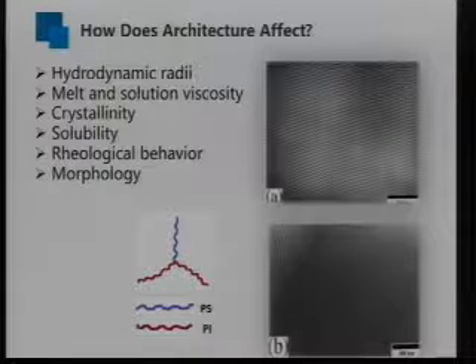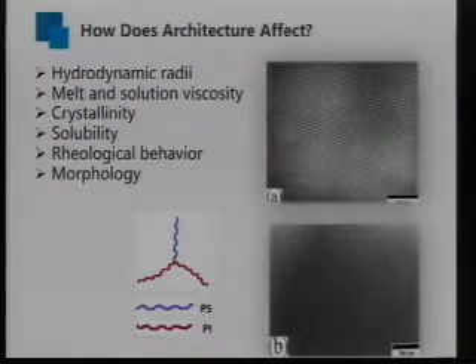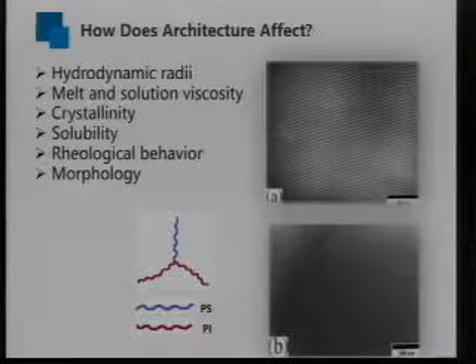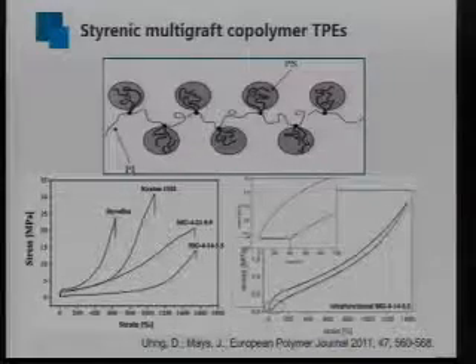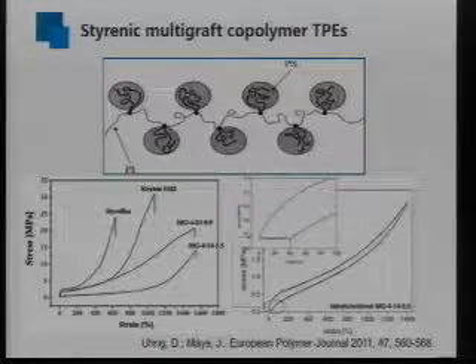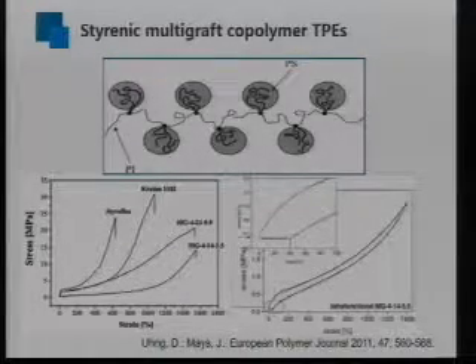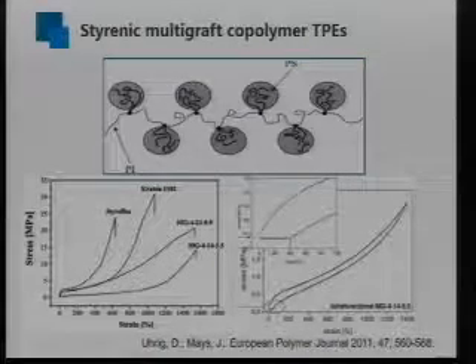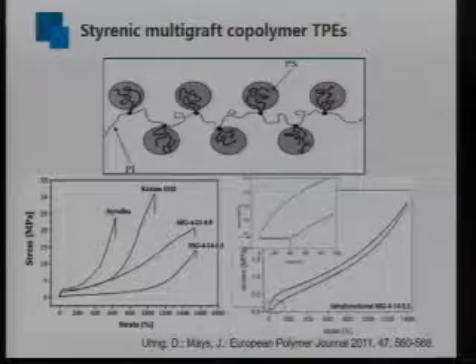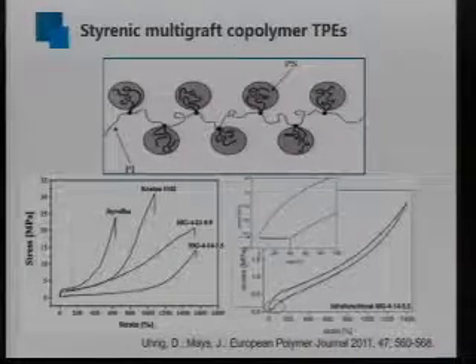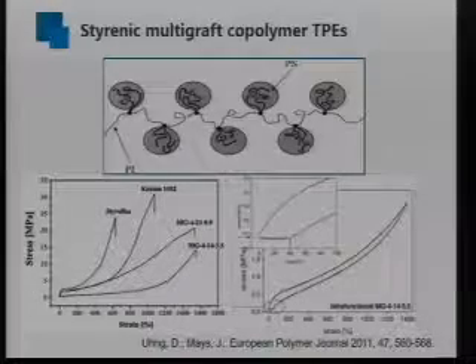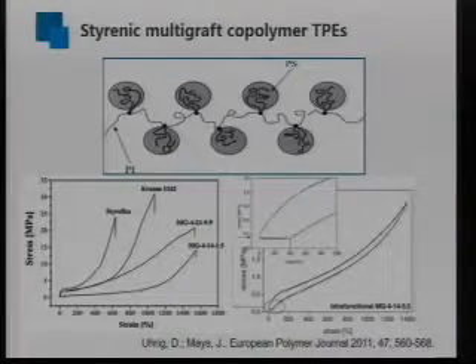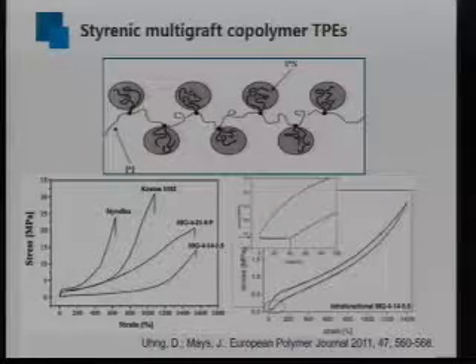For example, as reported by Dr. Pochan and Dr. Mays, this kind of tri-arm star composed of one polystyrene chain and two polyisoprene chains can phase separate into a cylindrical morphology with very long range order. So the Styrenic multigraft copolymer thermoplastic elastomer has been reported before, with polyisoprene as the main chain and polystyrene as the side arms. This multigraft copolymer can reach mechanical strengths comparable to the commercial linear type Styrenic thermoplastic elastomers, but with a much increased elongation, even higher than 1,500%.